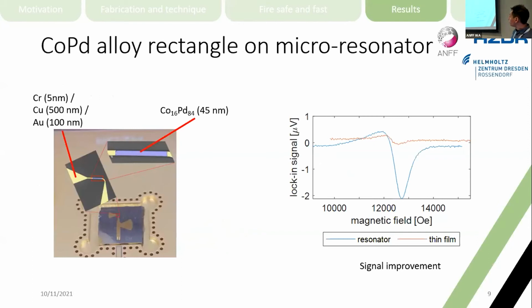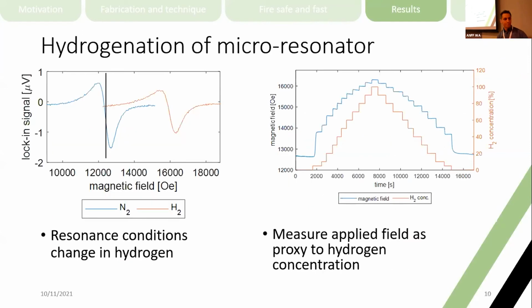Okay, now we use the resonator. Why do we use that resonator? Well, with the resonator structure, we create a standing electromagnetic wave. The magnetic field is what drives our resonance, and with that standing wave, which occurs just under the cobalt palladium sample there, we create a much stronger magnetic field for a given microwave power than when we just use a normal strip line with a thin film on top. And we see that nicely here on the right, where I show FMR spectroscopy traces for the resonator with a much larger signal than for the thin film.